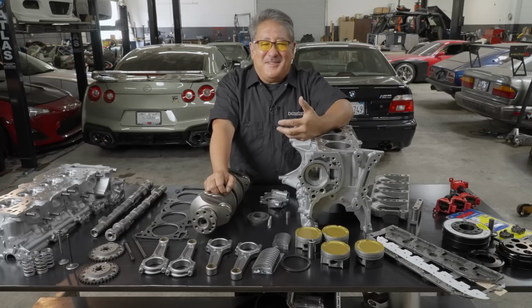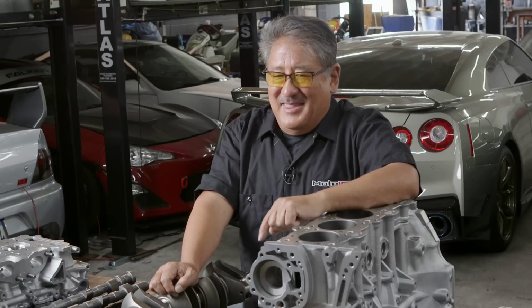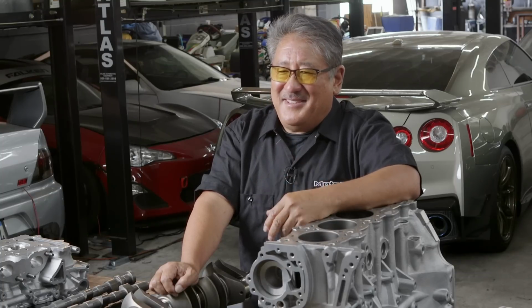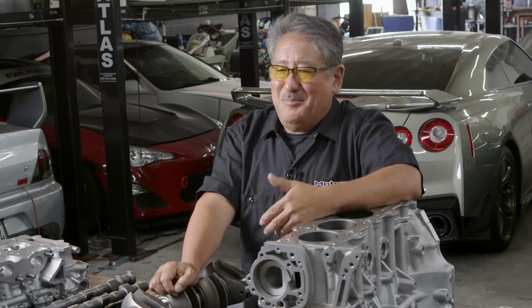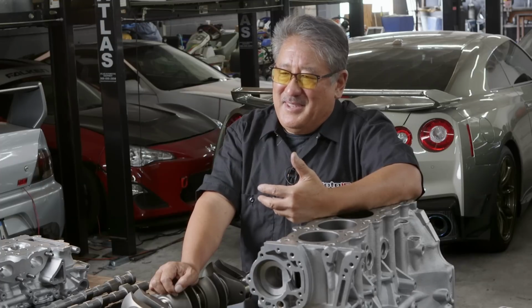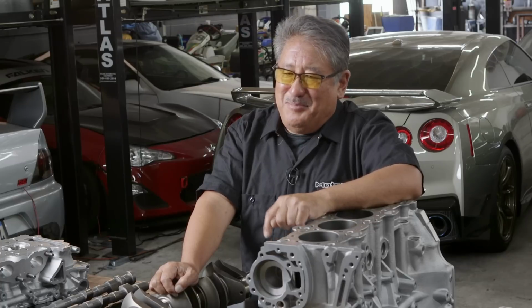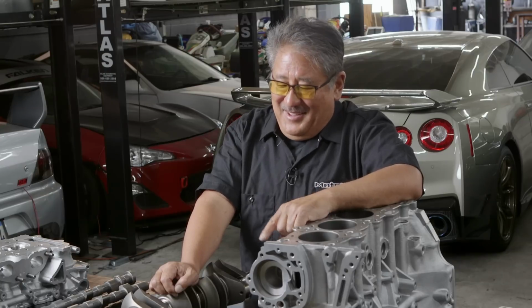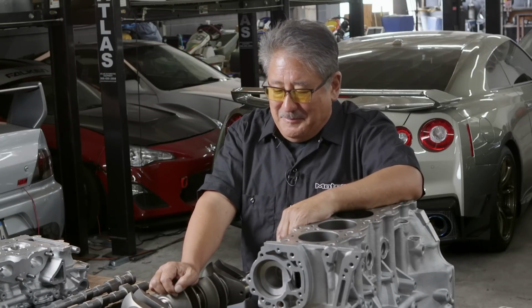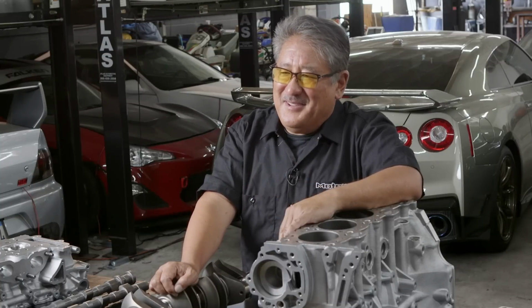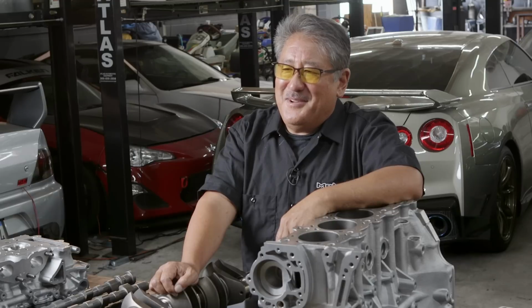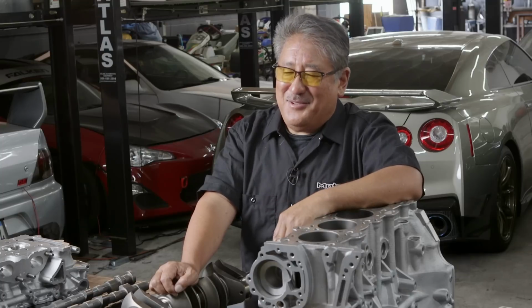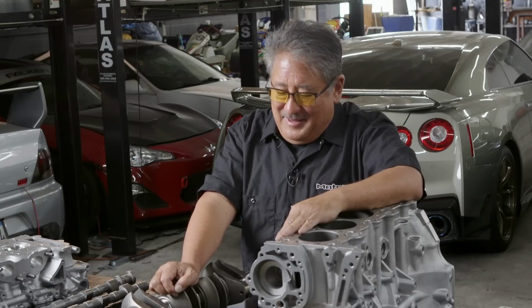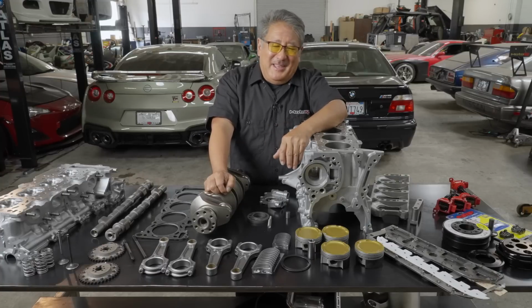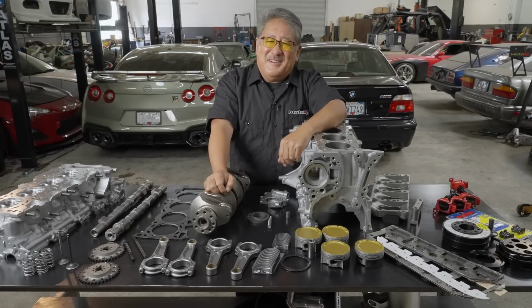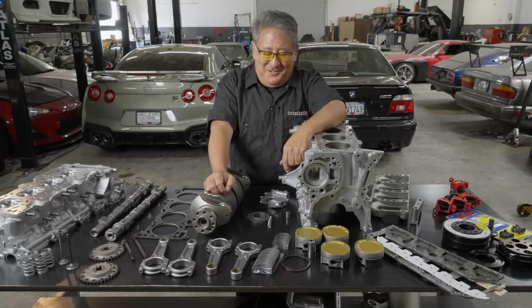There's probably a lot of copper in it too, because copper gives hardness and strength. And then there's a surface layer which has a higher lead content that's softer. This gives more what you call embeddability. So like if you get dirt particles in the oil, things like that, they can actually embed into the soft surface and not go around like sandpaper and damage your crank. So they kind of give the bearings some more forgivingness. But the base layer, which is copper, tin, antimony, and some lead, does the heavy lifting as far as taking the load on the bearing. And then there's a zinc overplating on the top, which gives it corrosion resistance and resists scuffing when the engine is first being started and getting its initial break-in.